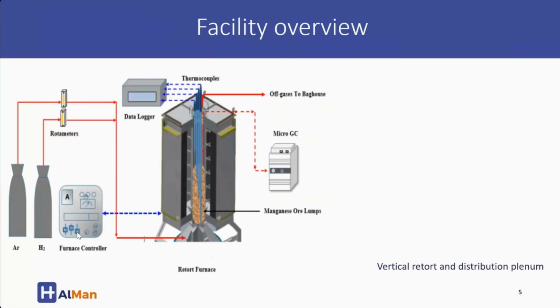For the pre-reduction work, we used our 200 kg capacity vertical retort furnace. The gas injection uses gas cylinders where flow rate is controlled using rotameters, and the gas is injected via an injection port located at the bottom of the tube.